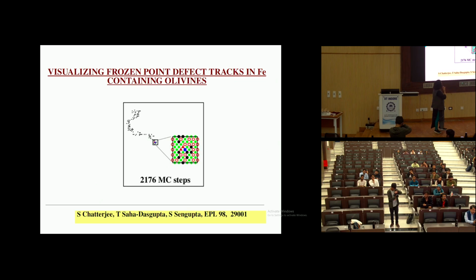Okay? More important is, experimentally, you cannot see a vacancy. You cannot measure them. It's an absence of something. So how do I measure it? In fact, there are some experimentalists in this audience. If you ask them how much percentage of vacancy you have, do you have an answer? No. You can't measure vacancy. You possibly know there are some vacancies, but you can't estimate the percentage of vacancy other than doing some chemical analysis, and you will find that that much percentage of some chemical component is missing. So possibly there are some vacancies. But if I ask you to track the vacancy, will you be able to track the vacancy?